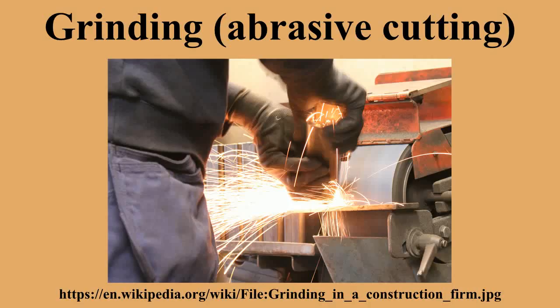Electrolytic in-process dressing grinding is one of the most accurate grinding methods. In this ultra-precision grinding technology, the grinding wheel is dressed electrochemically and in-process to maintain the accuracy of the grinding. An ELID cell consists of a metal-bonded grinding wheel, a cathode electrode, a pulse DC power supply, and electrolyte. The wheel is connected to the positive terminal of the DC power supply through a carbon brush, whereas the electrode is connected to the negative pole of the power supply.